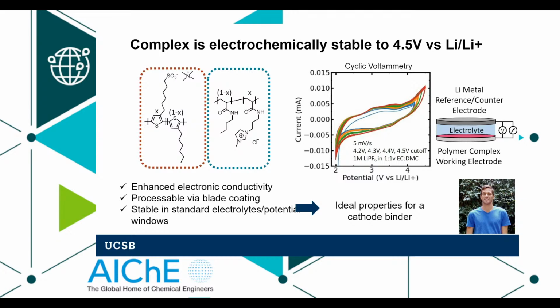The coacervate actually works really well in terms of electrochemical stability because it has those very, very stable ionic liquid type side chains as well as an aromatic backbone. So you're seeing by cyclic voltammetry, there's a very, very nice stable window relative to lithium. We think that combining that with enhanced electrical conductivity and the processability will give us the ideal properties